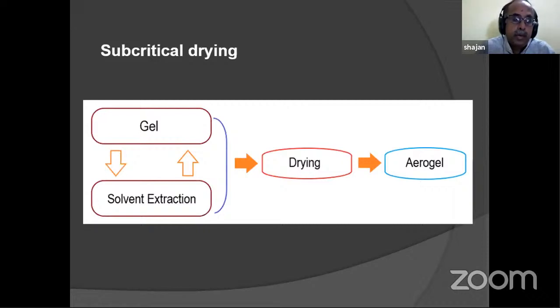So what you do, you prepare the gel, you put it inside a beaker or some vessel containing n-hexane or isopropyl alcohol. You exchange the solvent. This is very similar to the method we use in your house to wash clothes. If you want to remove the dirt on the clothes, you apply soap. And what soap does is it reduces the surface tension and automatically the dirt is removed. In a similar way, you are reducing the surface tension of the water or any solvent you take.